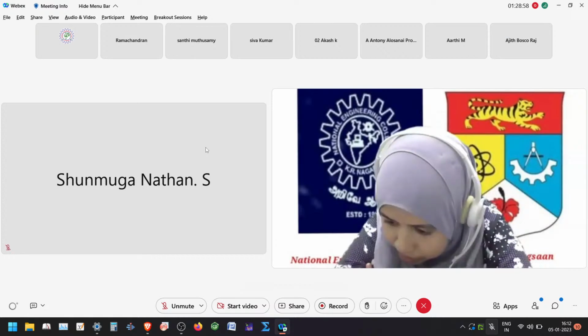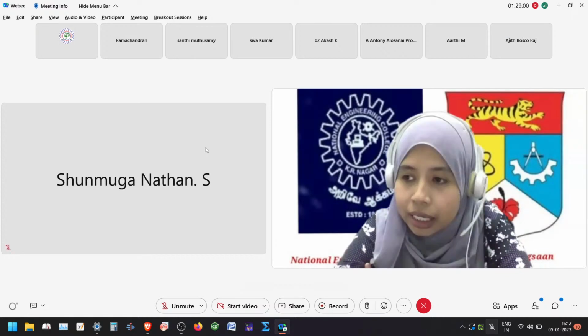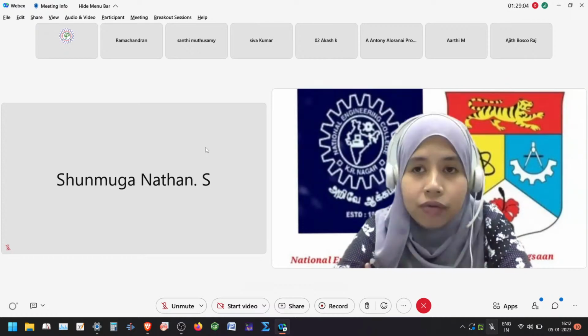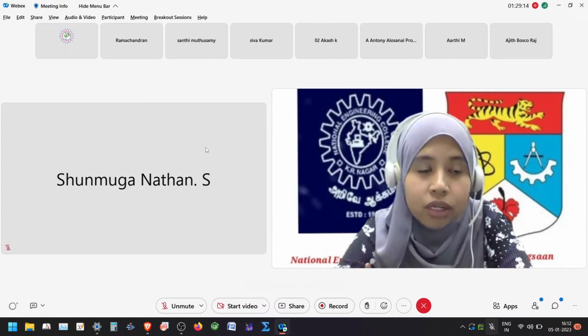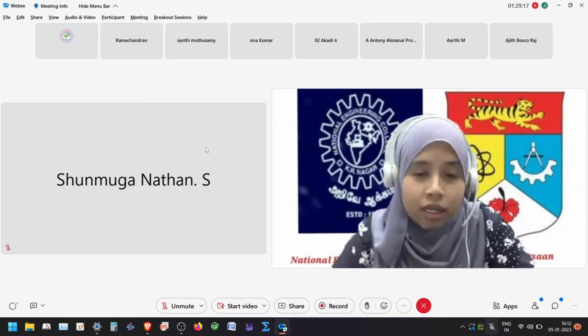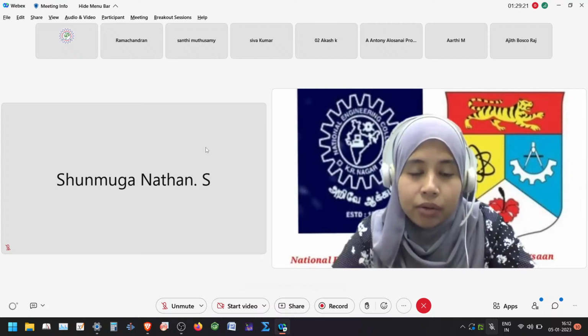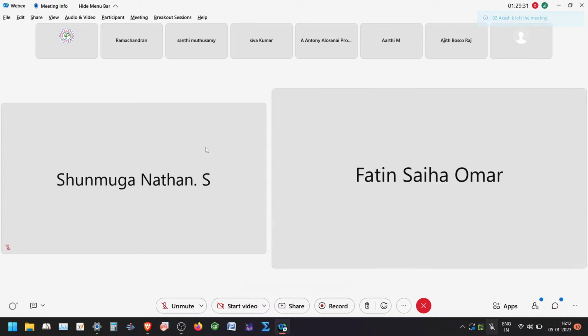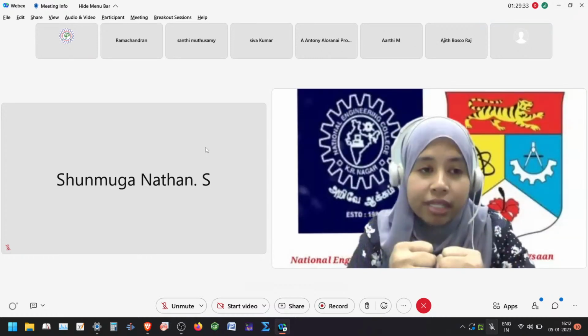Actually, the initial morphology won't change. For example, material A has a cube structure morphology, and material B has a sphere morphology. For a composite, if you mix cube with sphere, there will be no change in morphology. What you can see from the morphology is that the spheres will just attach to the cube. So that is for a composite. There will be no change in the lattice structure of the materials, because they just combine physically.